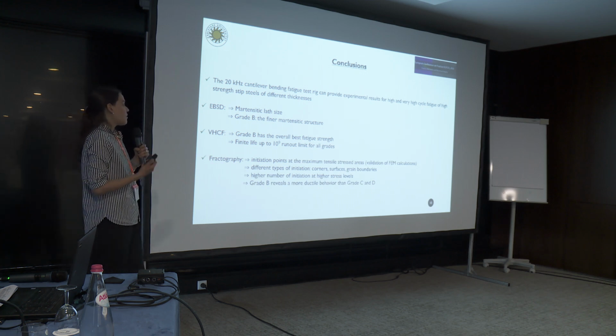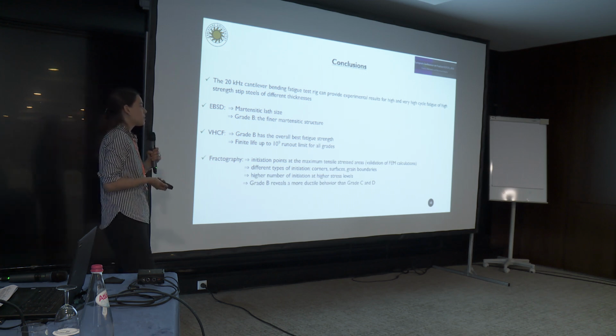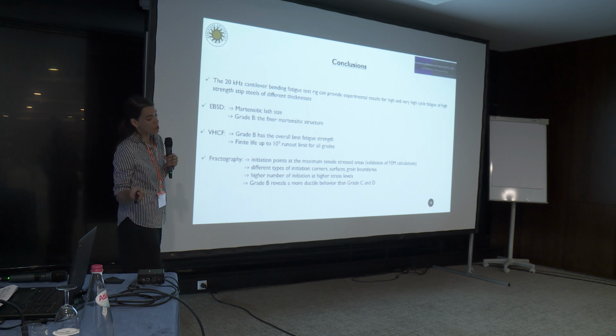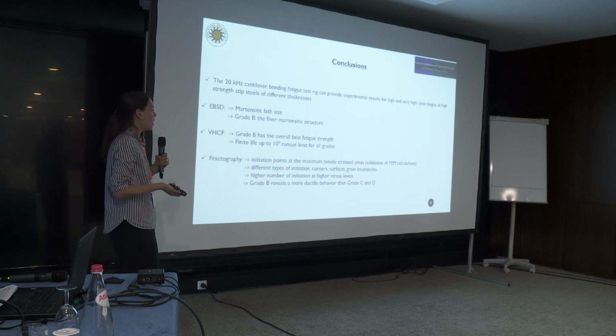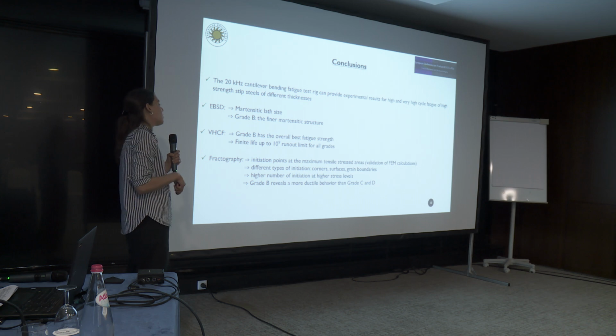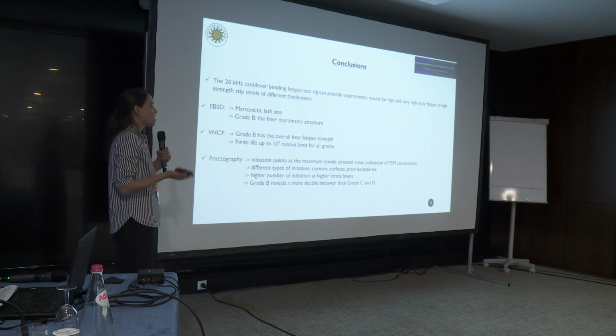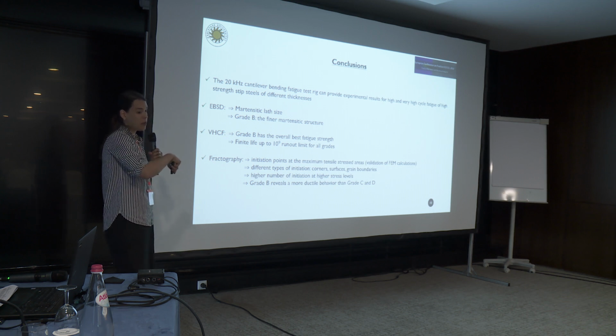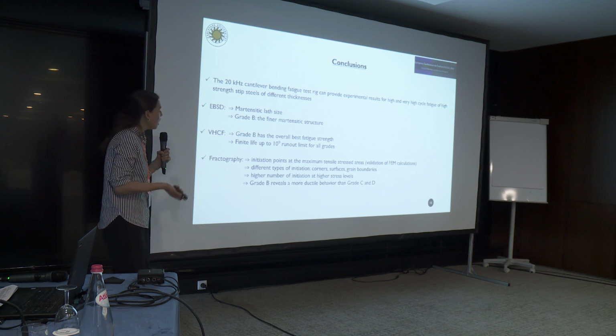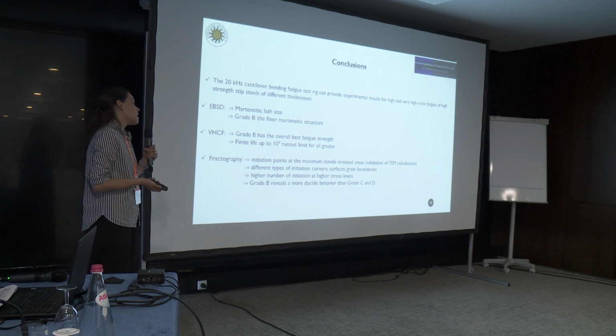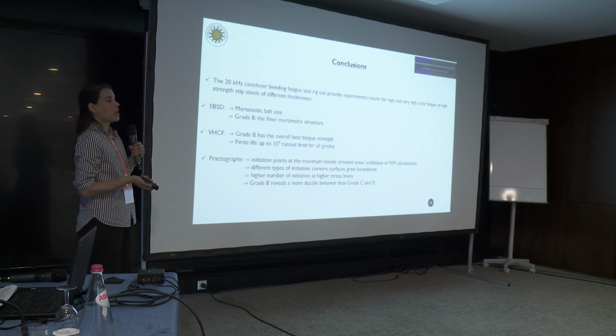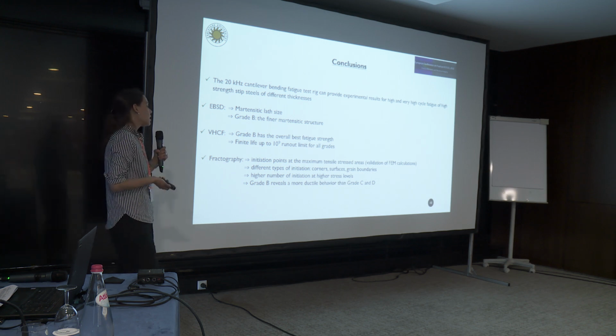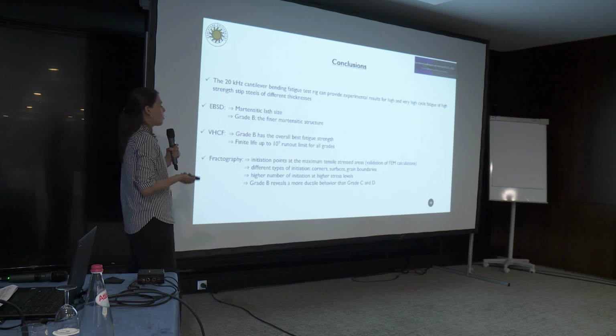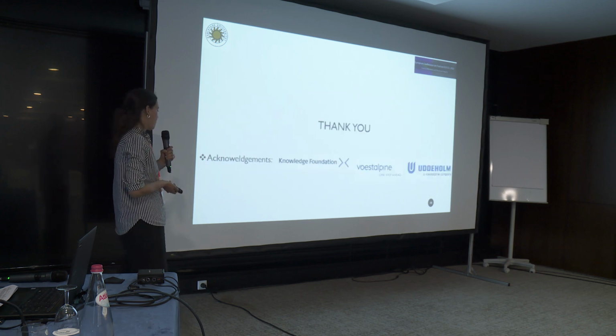The fractography reveals different initiation points at the maximum tensile stressed area, which at the same time validated the FEM calculations. We had different types of initiations like corners, surfaces, or grain boundaries, which were correlated either to the process or the microstructure. There was a high number of initiation points, especially at higher stress levels, and grade B reveals a more ductile behavior than grades C and D.